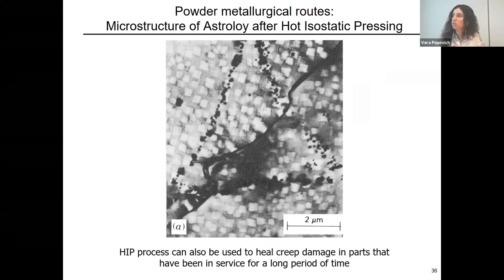And for hot isostatic pressing, especially when you deal with materials, you take a certain cast material, you use spray atomization, so you spray it in the form of a powder. So it's a powder metallurgical route, this technique. Then you use a container that usually is a bit larger in shape to allow for slight changes during the high temperature application. And then you apply the hydrostatic pressing under vacuum and high temperature.